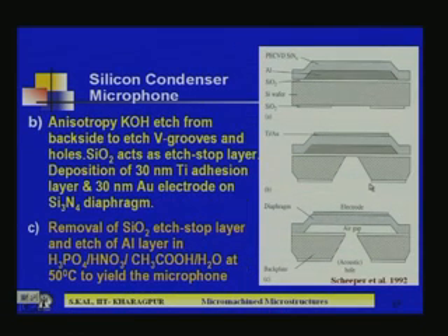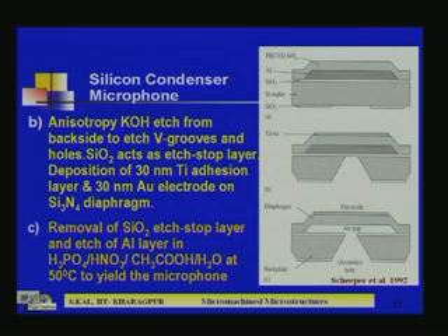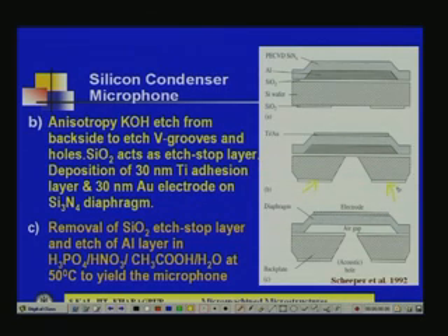You see, the anisotropic KOH etch from the back side has been done. After that, you will get this kind of V groove. Silicon dioxide in this particular location here and here will act as the etch stop layer, and this silicon dioxide here is also working as an etch stop layer, because silicon will be etched from the backside here and here. And after etching, it will face silicon dioxide, then it will stop there. So, that means, in the structure you are getting a membrane like this.